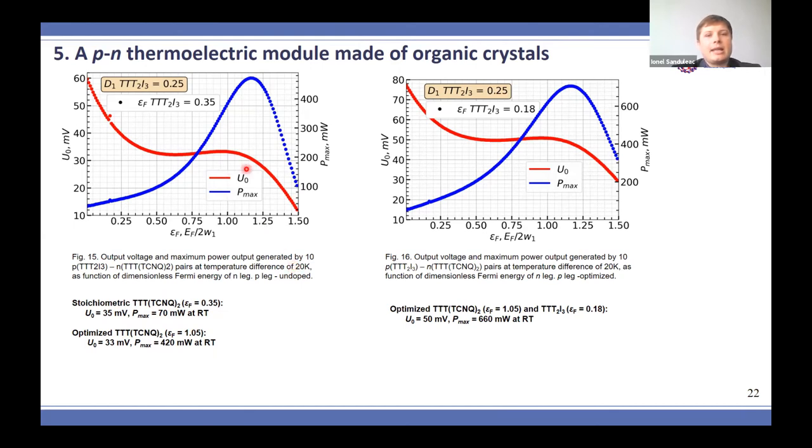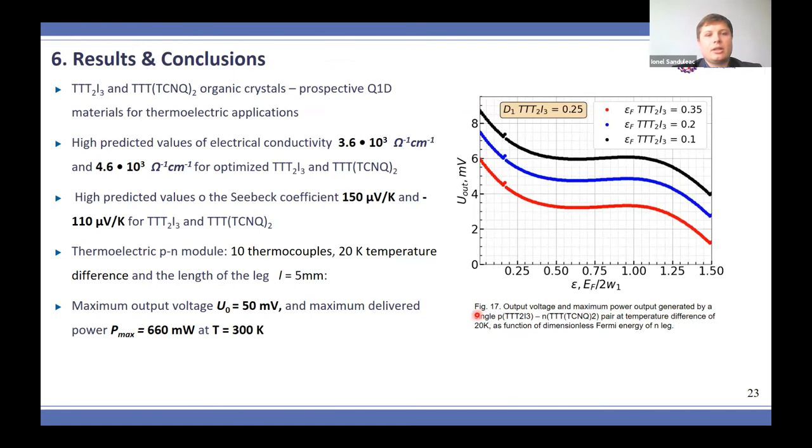And also by improving the properties, namely by diminishing the charge carrier concentration in the P-type crystal, as you can see, the delivered voltage can be significantly increased, and the power factor is an order of magnitude higher in this case. So as a conclusion, we can predict that a thermoelectric module made of these crystals can be very successfully applied for biomedical applications as thermoelectric sensors, as infrared sensors, or as thermoelectric coolers. Of course, the main methodology for improving the properties of such crystals is well known and is well described in our papers. And it was also proved experimentally that such procedures are applicable and provide very good results.